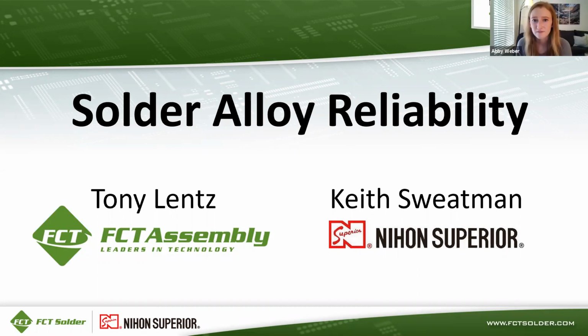How does solder paste flux affect reliability of electronics? Well, solder paste flux, which wasn't really the topic of this conversation, certainly has an effect on reliability, especially no clean solder paste fluxes, which are left on the assembly. And depending on the conditions in which they're used and how they're handled, no clean fluxes can sometimes cause failures over the life of a circuit board, because there can be unreacted activators or potentially halogens left behind in a flux residue. And if that flux residue is disturbed, those things could create corrosion or electrochemical migration or dendritic growth over the life of the assembly. Great, thank you.